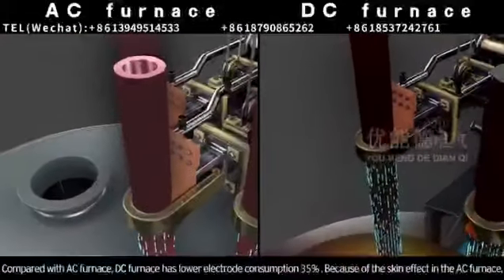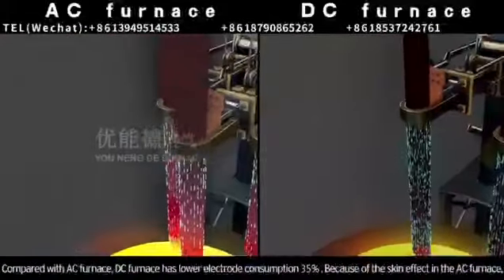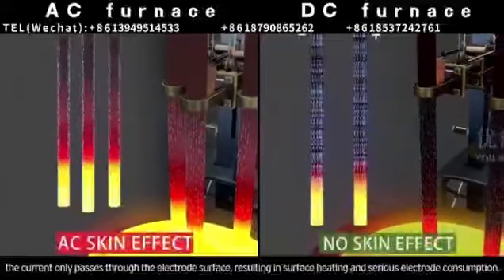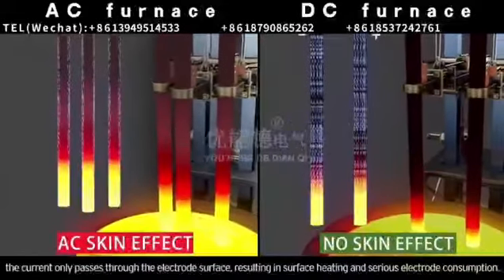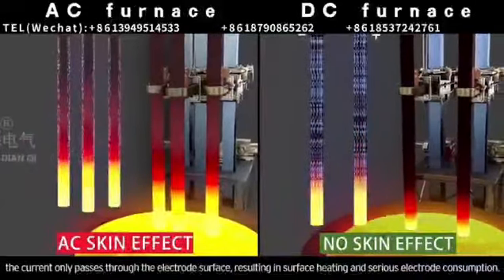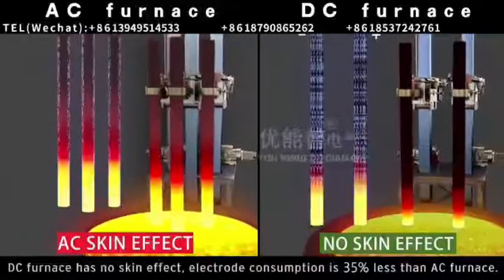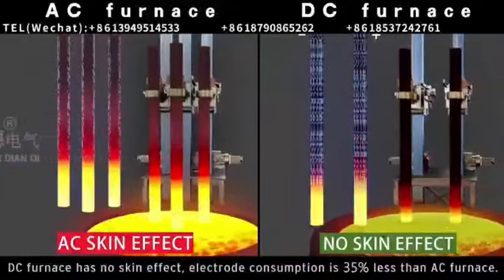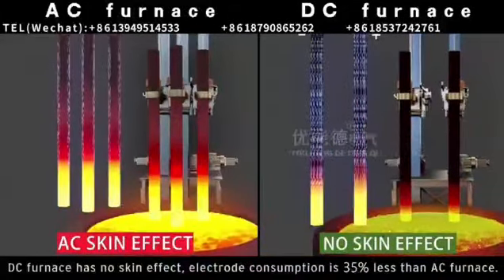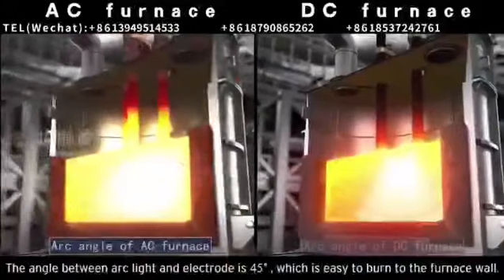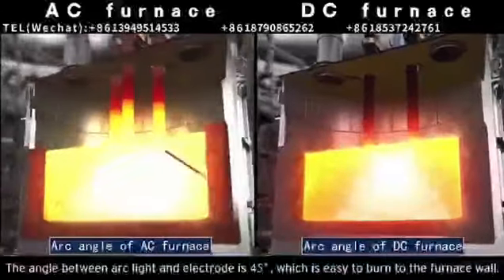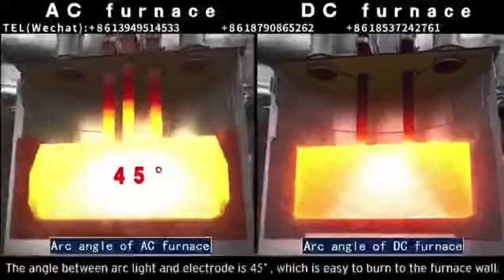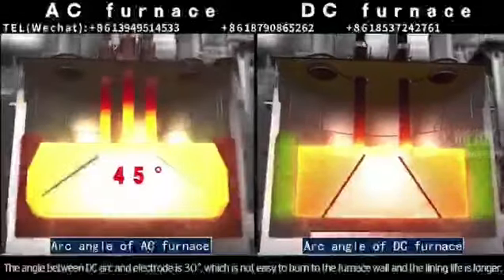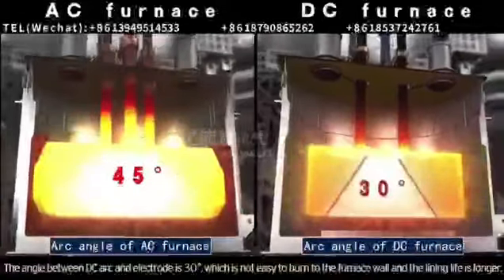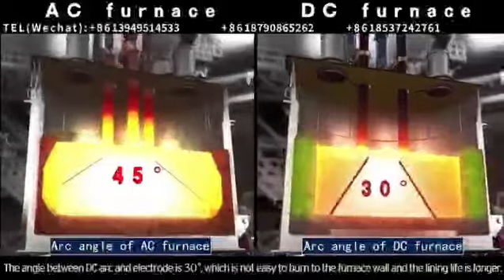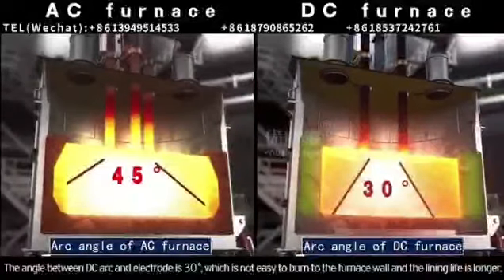Because of the skin effect in the AC furnace, the current only passes through the electrode surface, resulting in surface heating and serious electrode consumption. DC furnace has no skin effect. Electrode consumption is 35% less than AC furnace. The angle between AC arc light and electrode is 45 degrees, which is easy to burn into the furnace wall. The angle between DC arc and electrode is 30 degrees, which is not easy to burn to the furnace wall, and the lining life is longer.